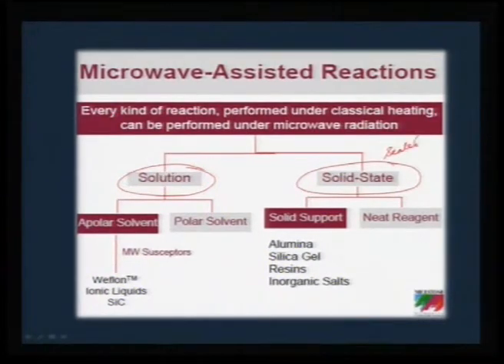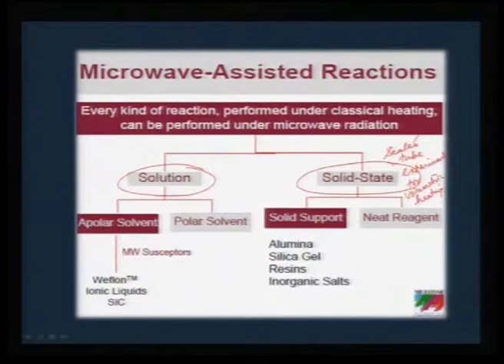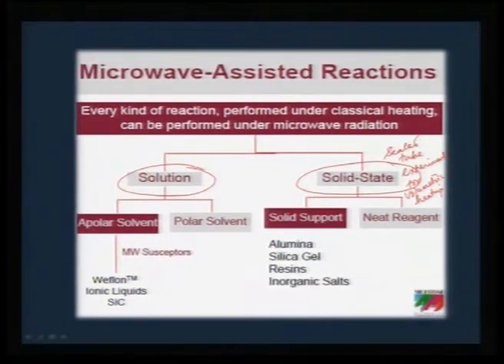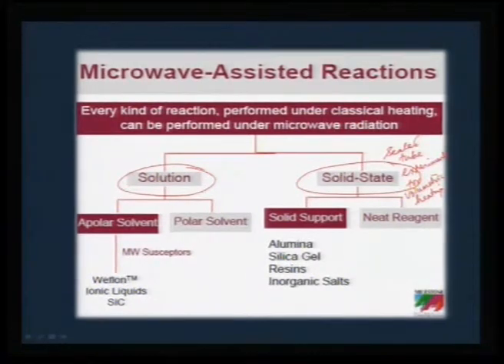Vacuum sealed capsules can be used for solid-state reactions to bring solid-solid interaction into closer proximity. When solids couple with microwave, a plasma is generated and this plasma can bring about volumetric heating; therefore this is done in seal-tube experiments mostly for volumetric heating. Neat reagents are possible as well as solid supports. Variety of solid-state reactions can be achieved; similarly, solutions can be tried with apolar, aprotic, and polar solvents. For apolar solvents, some microwave susceptors need to be induced to bring about microwave coupling.